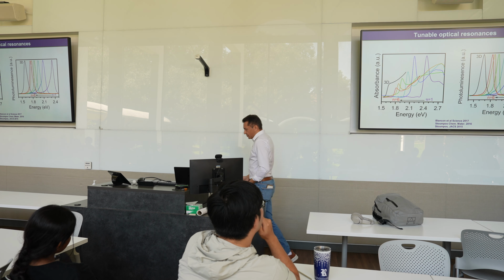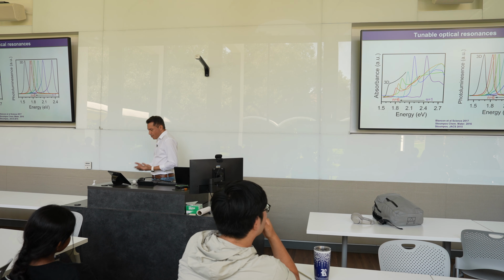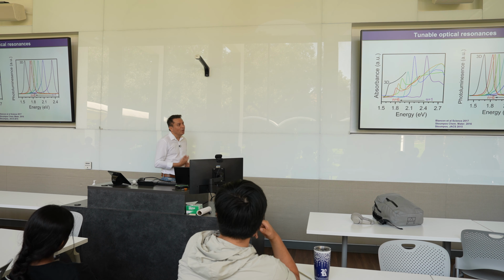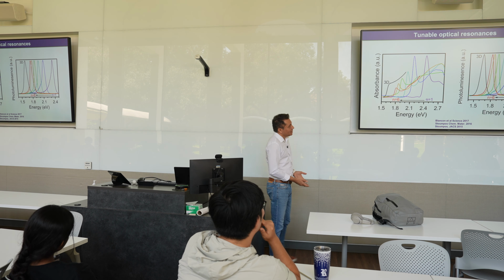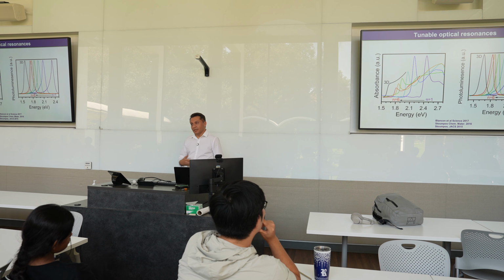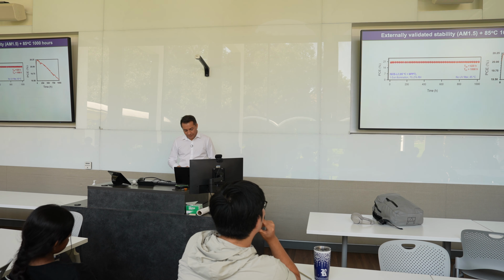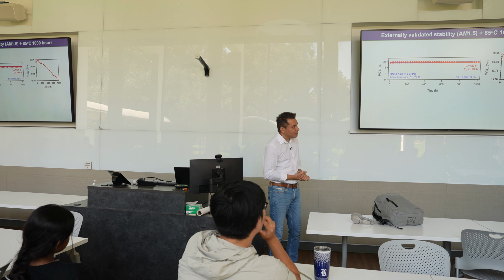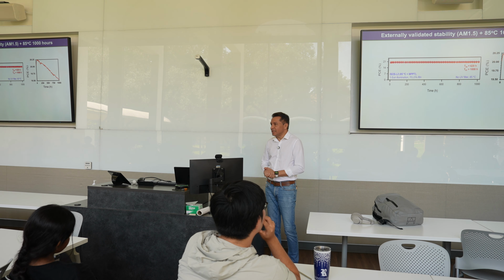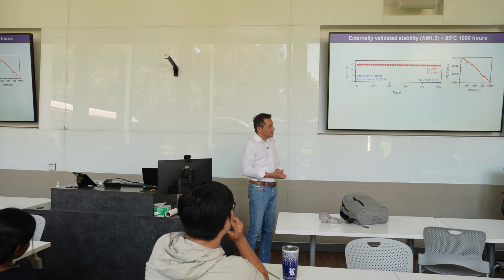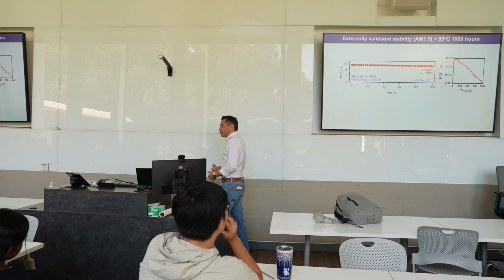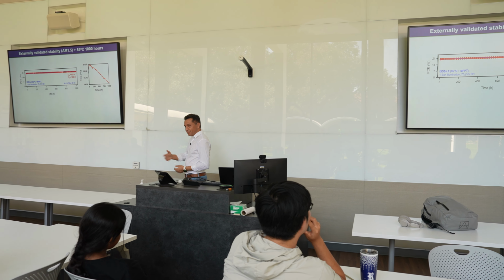And one of the things our lab has been really famous for is, as I mentioned, the bane of these materials is stability, long-term stability. And so we hold the record now for the 3rd year, we just had this, for the most stable perovskite in the world, right? And so we're working with a lot of companies in trying to license these things out. And in fact, the litmus test for this is this paper that we published. This is an accelerated aging test that you would do on a solar cell made of this, right? You would take this solar cell, put it at 85 degrees C and put light on it and forget about it, right?